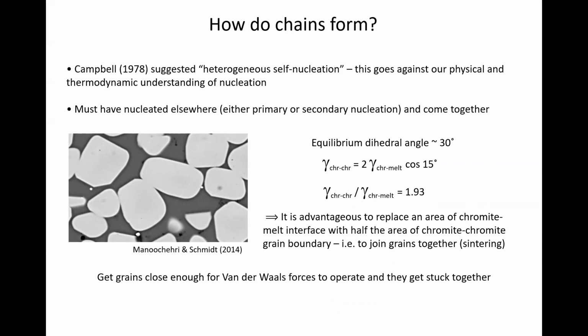So if you've got 2 grains and they come together to form a grain boundary, what you've done is replace twice the area of the chromite melt interface by the chromite grain boundary. And that's actually energetically advantageous to do. There's an energy drop when you form a grain boundary between those 2 previously isolated grains. So all you have to do is bring them close enough together so they can see each other by van der Waals forces, and they're going to go kaping, and they're going to sinter together and form a grain boundary.